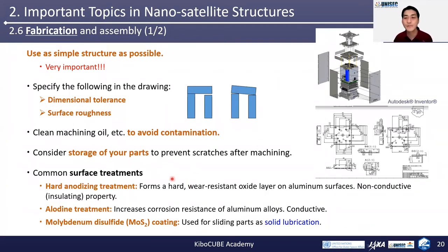There are commonly used surface treatments. The first is hard anodizing treatment. This forms a hard wear-resistant oxide layer on the aluminum surface. This layer has non-conductive properties. The second is an Alodine treatment. This increases the corrosion resistance of aluminum alloys. The surface becomes conductive. And finally, MoS2 coating is often used for sliding parts as a solid lubricant.